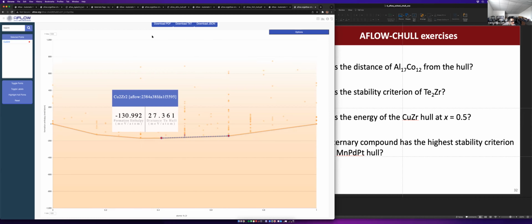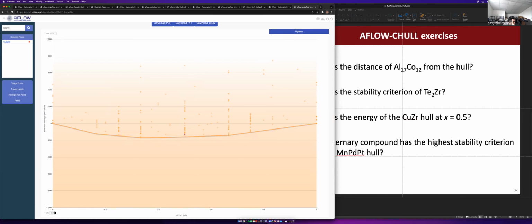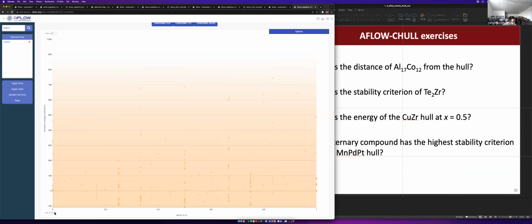By eye, you can actually even see it better if we change the y-axis here. No, we want to go higher. If you want to zoom in, you can change this value here. Let's see if we do 200. It's a little difficult to play with, but you can do that, and you'll see that the distance to the hull is around, I think, 40 or 50 meV per atom.